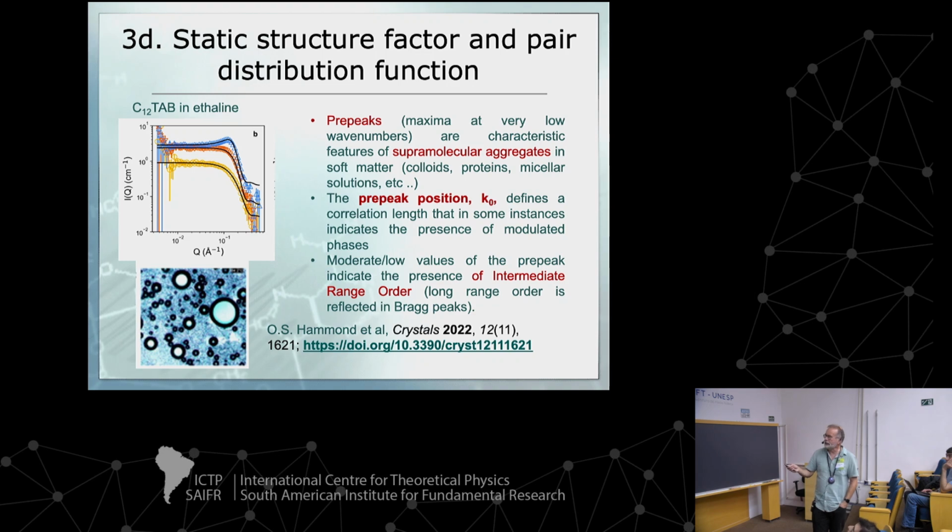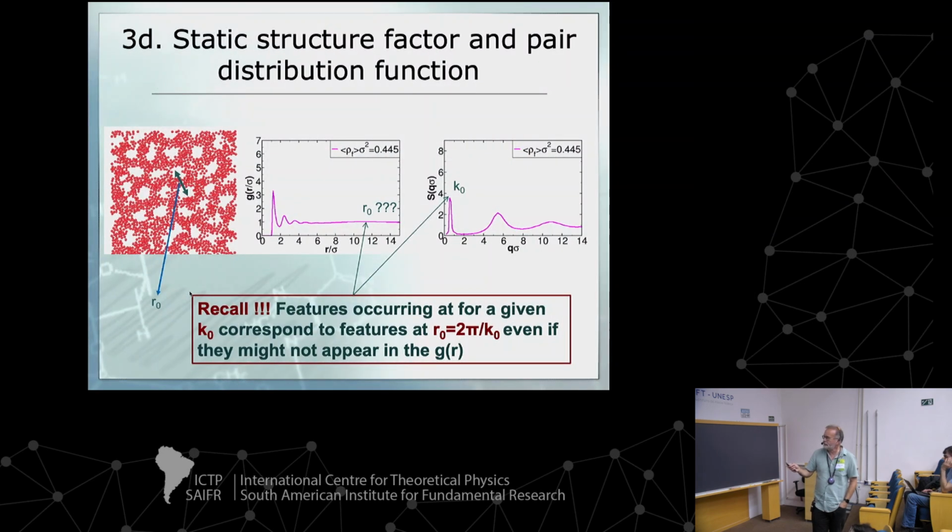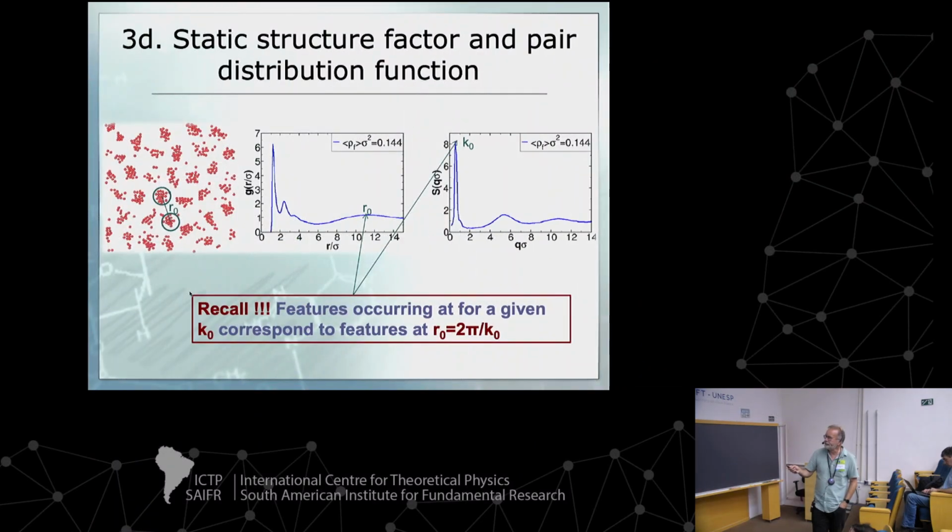Notice that in the case that we studied before, the clusters are not that polydisperse. Actually, if you look at the distribution of clusters here, you see that this is a beta-shaped distribution that is relatively narrow. And that's because of the particular type of interaction that has this feature that I drew for you yesterday. That has this maximum when you have the equilibrium between repulsive and attractive forces, right? So it's much more controlled in this respect.